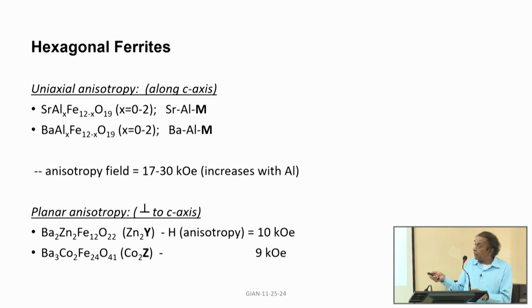So, M type has a uniaxial anisotropy field, it is very high, it can be 17 to 30 kilooersted, and the Z and Y types can have in-plane anisotropy a little bit less than M type, like 9 to 10 kilooersted.